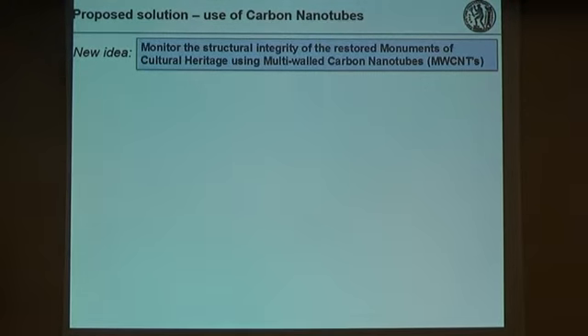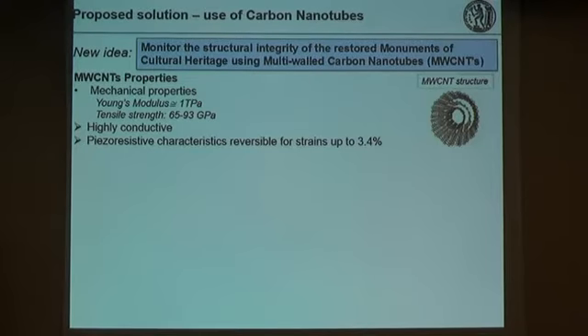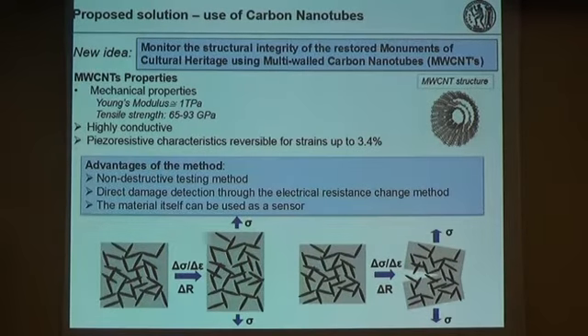Our idea is to use innovative carbon nanotubes in order to reinforce the filling material, the mortar, and to use this nano-reinforced mortar in order to monitor the structural integrity of the restored monuments. And we decided to use carbon nanotubes due to their exceptional piezoresistive characteristics. This means that their electrical properties change according to the applied stress and strain. So what we wanted to do is to develop a smart material that can be used as a sensor by recording its electrical resistance change, which is a non-destructive testing method.